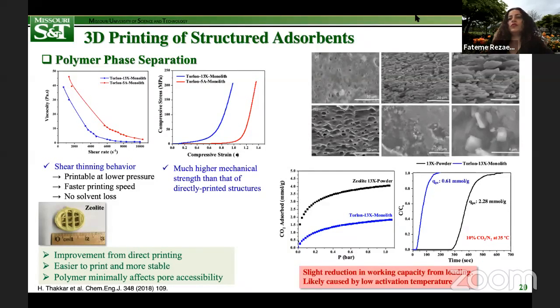To have good flowing characteristics, we need a low viscosity ink or paste. A high viscosity is usually obtained at low shear rates. So this is the relationship that we found for these materials. And low viscosities at high shear rates are favorable in order to have good extrusion behavior for our monoliths.